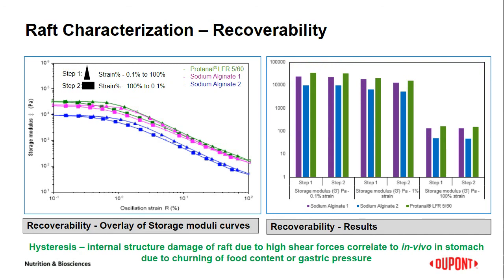So moving to the next results, that is about the recoverability. On the left side of the chart, we can see the overlay of the storage modulus curves for the different formulations obtained from the experiment. The formulations showed the recoverability of the raft to increase and decrease in the strain percentage, correlating to the recoverability of the raft when encountered with shear forces in the stomach under in-vivo conditions. The extent or magnitude of the hysteresis signifies the damage to the internal structure of the raft due to higher forces correlating to the in-vivo conditions in the stomach. The results obtained from the recovery experiments are presented in graph format on the right side, where the different strains in step 1 and step 2 are presented.